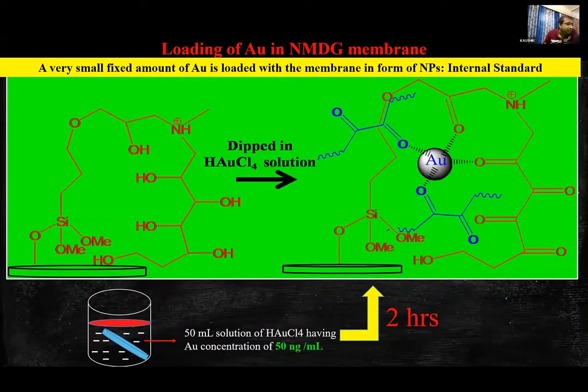Now, as we all know, in TXRF we need some type of internal standard. If there is any change in the counting statistics due to a change in the surface morphology of the membrane, or due to a change in the calibration of the instrument, or due to geometric factors, all these things can change the count rate. But if we use an internal standard, all these things will be taken care of. That's why it is very important to use an internal standard during TXRF measurement.